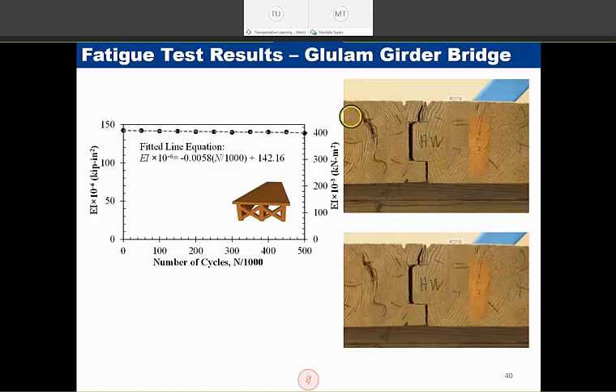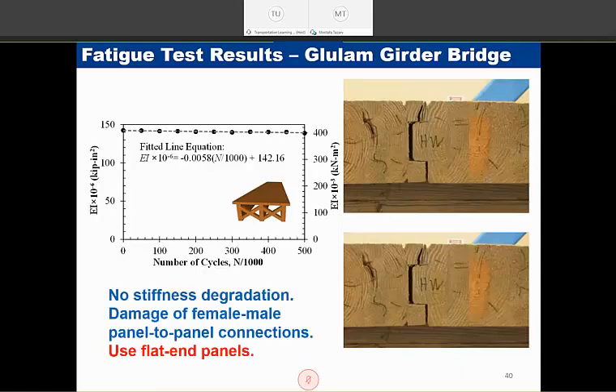However, the only significant damage observed during the fatigue test was at the tongue and groove male-female joint of the panels. To avoid this damage, our recommendation is do not use this shape. Just use flat panel to panel joints and use epoxy in between to make sure that there is no such damage during the life of the bridge.